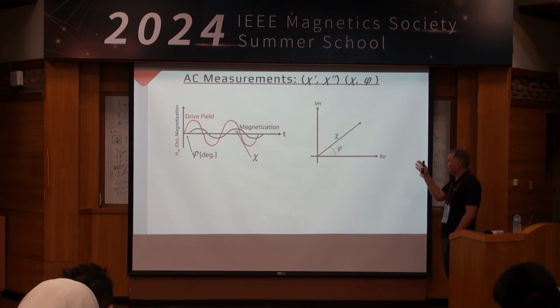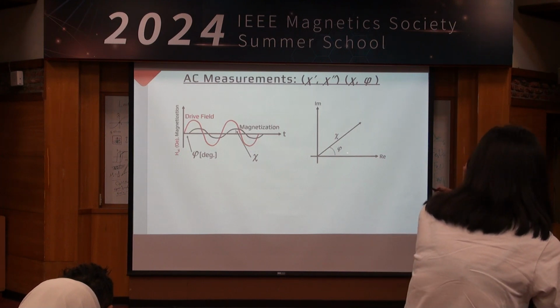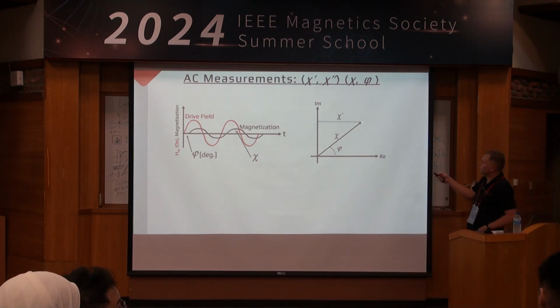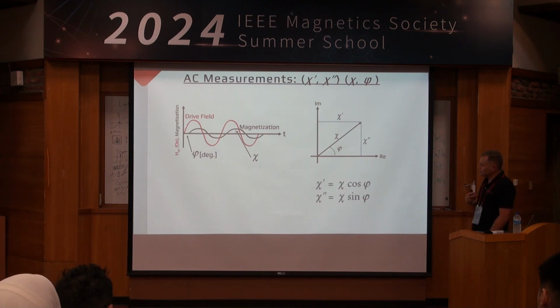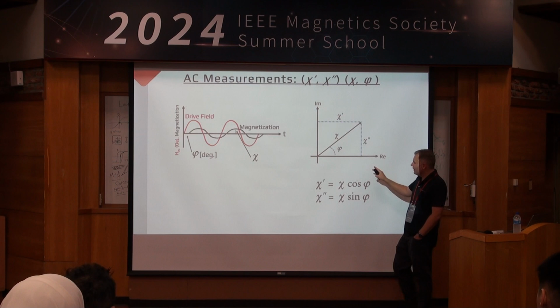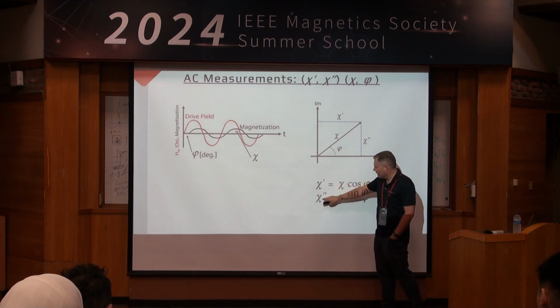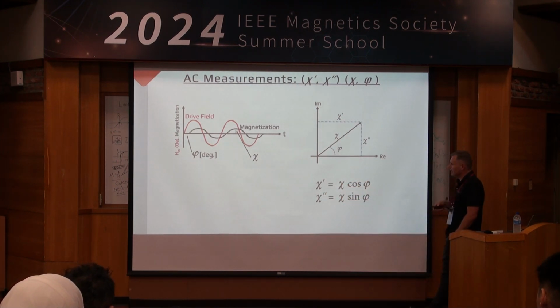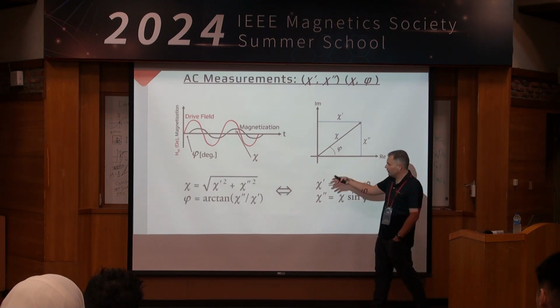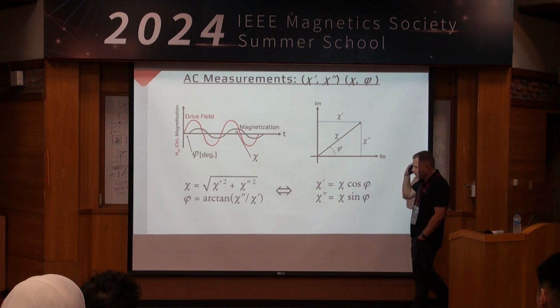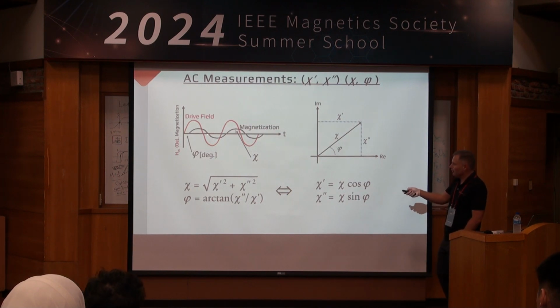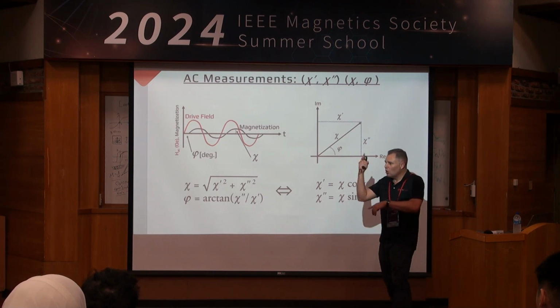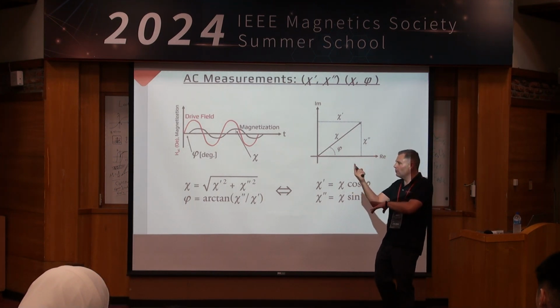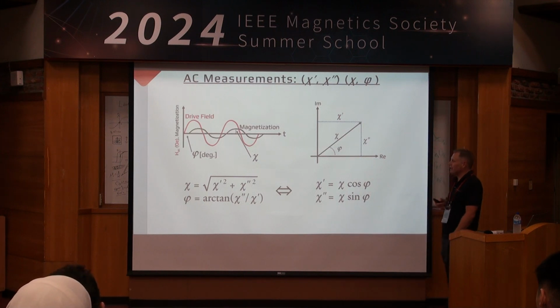So if we map this out in the complex plane, we've got an amplitude and a phase, or if you'd rather, we can think in terms of a real and an imaginary component as well. As it turns out, with the equipment from Quantum Design, at least, we naturally measure the real and imaginary components of the AC susceptibility, and then we calculate, through just trigonometry, the amplitude and phase. Most people have an easier time thinking in terms of amplitude and phase, though. So you can see it's fundamentally a very different type of measurement than a DC moment. We're curious how the magnetization or moment vector is now responding to this AC magnetic field.